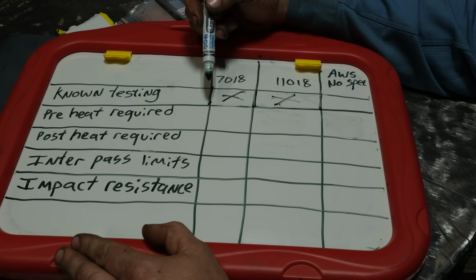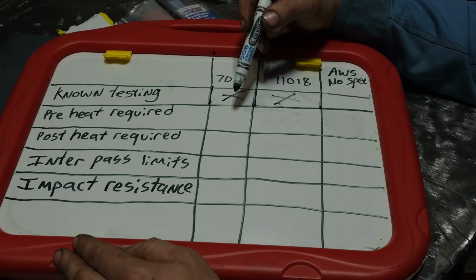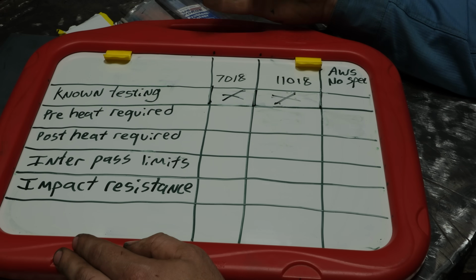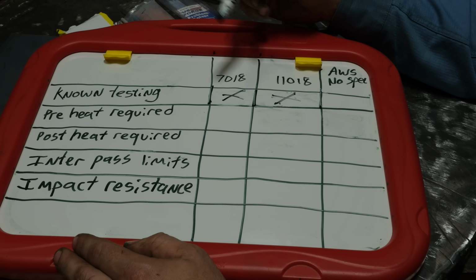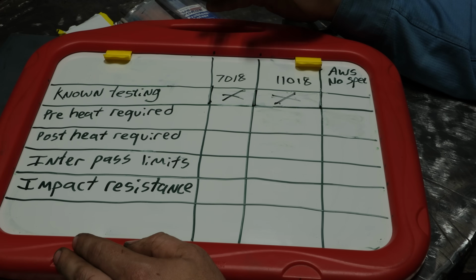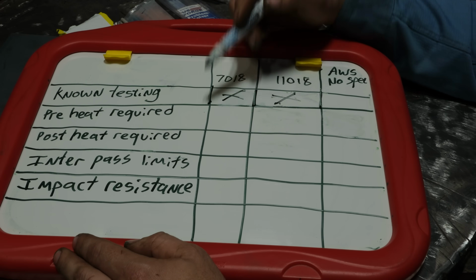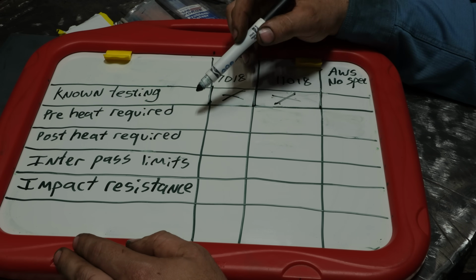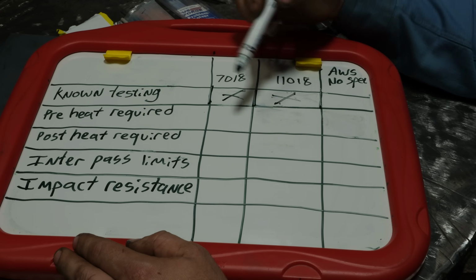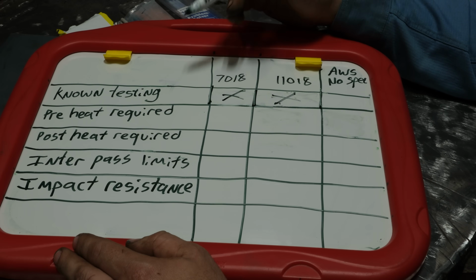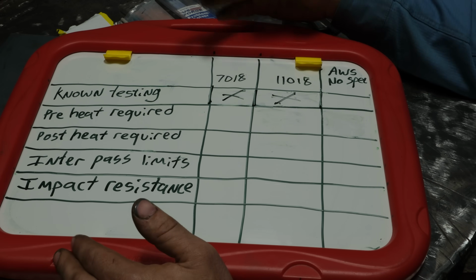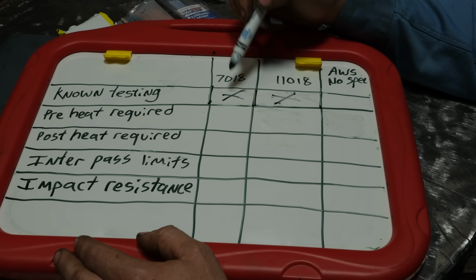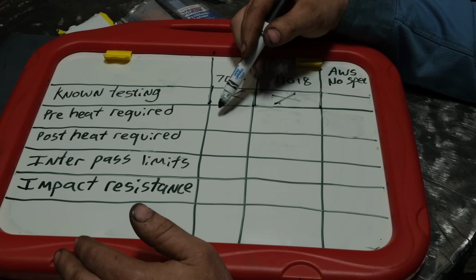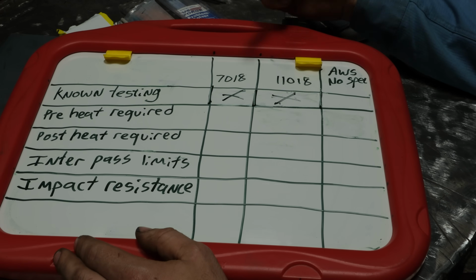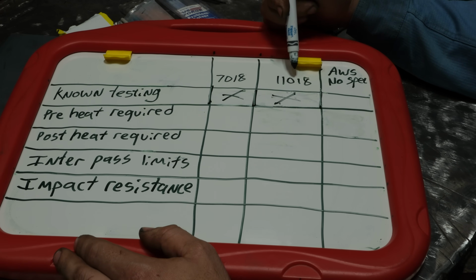High strength steel often requires a preheat to a minimum temperature. That could be because the material's hot short sensitive. It could be because if the weld cools fast enough, it shrinks and cracks. So it could be for the base material, it could be for the rod, it could be for any number of things. So a preheat is not required typically with 70/18 to weld mild steel. Now, if it's -60 out, you probably would want to do that. But for just room temperature steel, no preheat is required with 70/18 on mild steel.